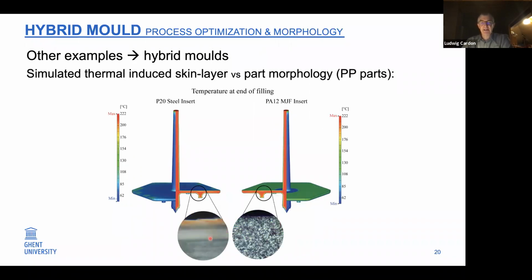So that's what we investigate, for instance, and you see that here on the bottom, on the left side, it's a standard skin layer you see in a steel mold when you inject the polymer, and here you have a little bit your spherulitic structure with semi-crystalline polypropylene material. But then you see in this one, you almost have no skin layer in contact with the cold plastic mold, but inside you see a lot of spherulites which are initiated due to the very slow cooling down. What's now important in that one, we are further investigating this topic the next months.